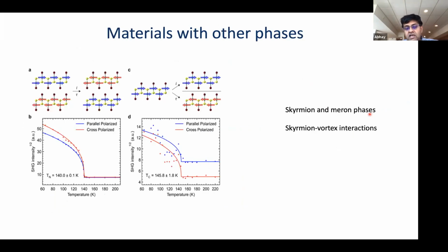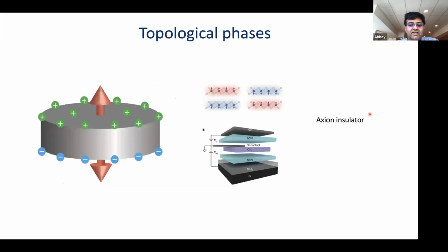And all of these things that I've talked about so far are with fairly boring materials, in the sense that we started with graphene and a semiconductor, which are kind of the simplest things. One can play these same games with magnetic structures, where if I have 2 magnetic structures with cross ferromagnetic directions in the 2 layers, you can create Dzyaloshinskii-Moriya type interactions. You can stabilize skyrmion phases, at least in theory, or meron phases, and we're looking for these sorts of things. One can couple that to a superconductor and look at interactions between skyrmions and vortices. In theory land, life is very easy, maybe not so much in experiment.